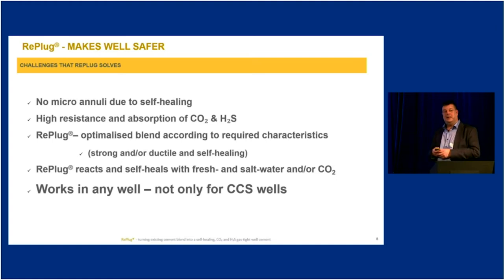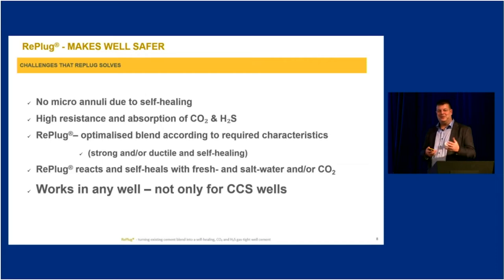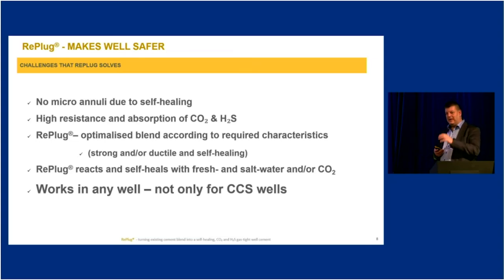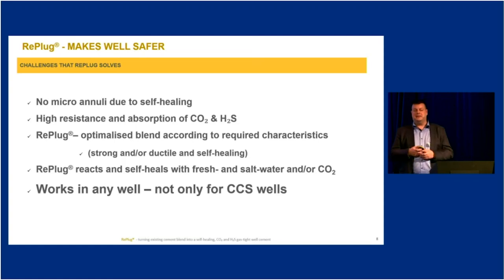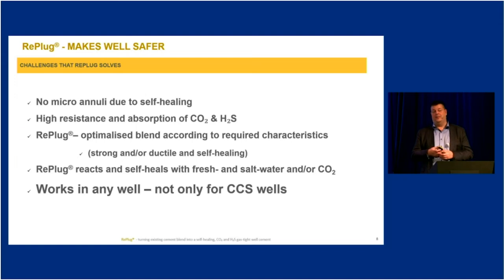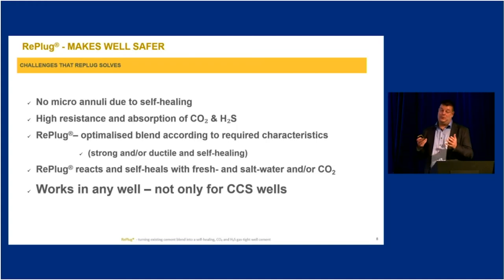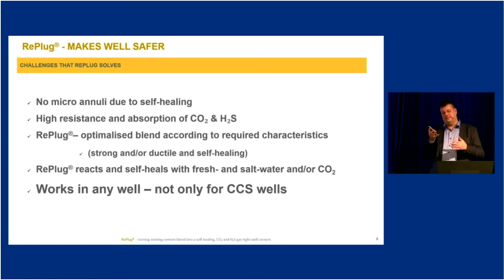CO2 is good for our product. And we also say that when you mix your cement, how often don't you test the chloride content of your mixing water because you want your mixing water to be clean? Well, we like when it's dirty — it just accelerates the process. And this is not a process that takes years and decades. We're talking about weeks, days, and months, as long as it's exposed to water, pressure, and temperature. It goes on and on. So if you have flowing water or CO2, then it will go on and on until it has expanded fully the 30%.